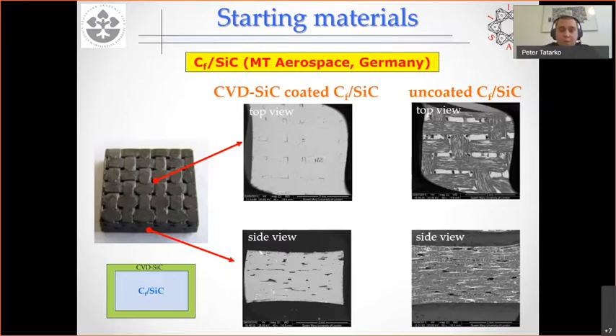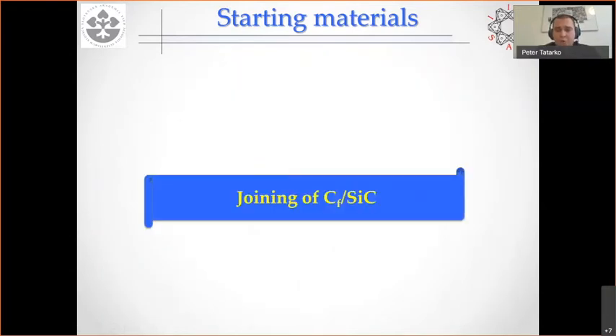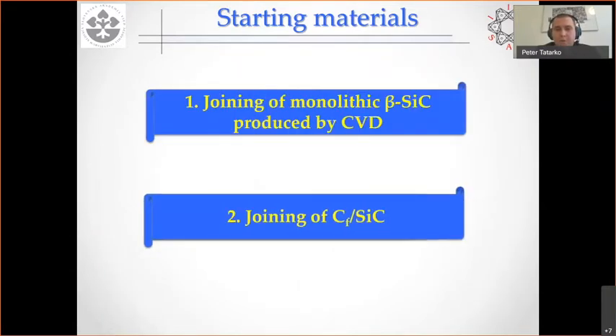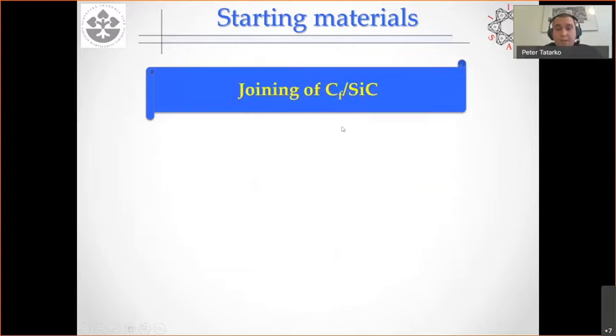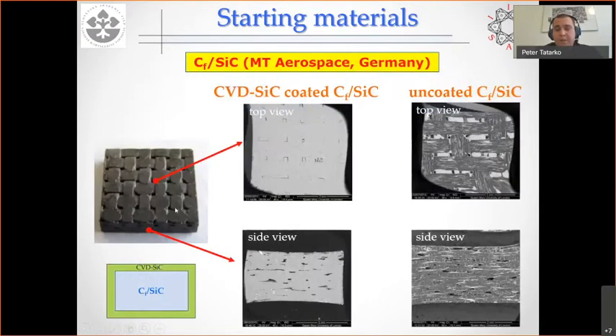Because these materials are always covered by CVD silicon carbide, instead of joining carbon fiber reinforced silicon carbide directly, we started optimizing our joining process using monolithic beta silicon carbide produced by CVD, because in the end it is the same interface that comes into contact when you want to make a joint.